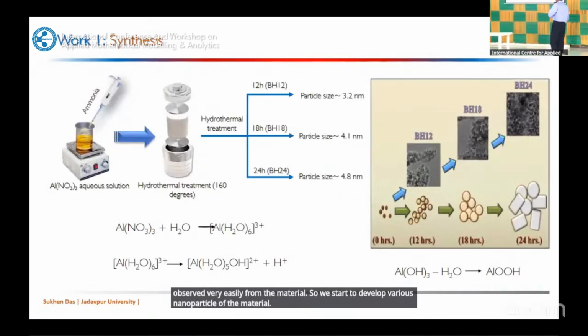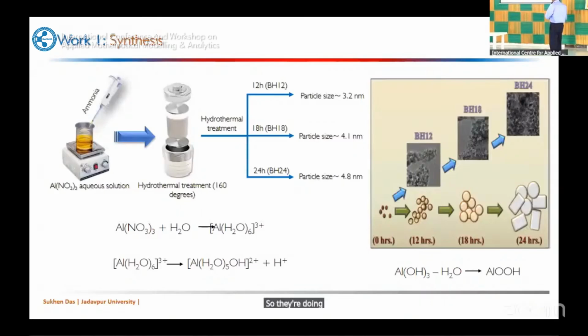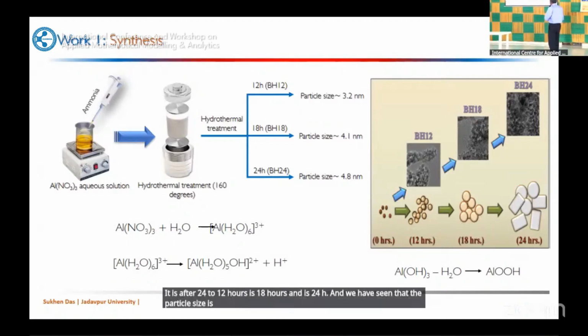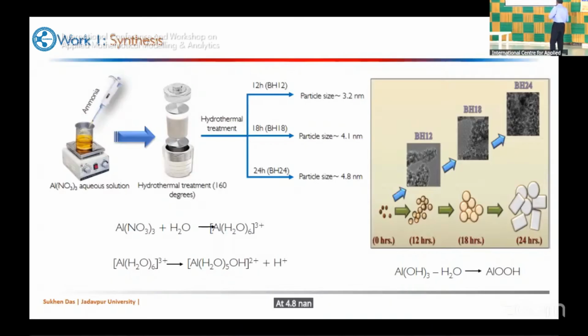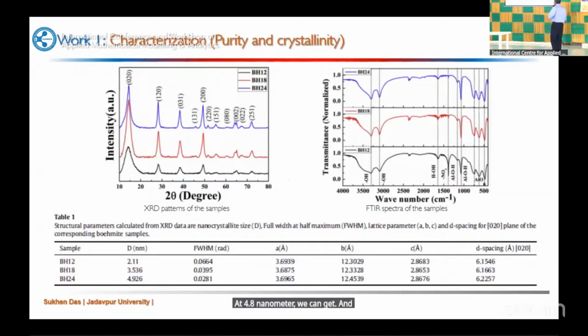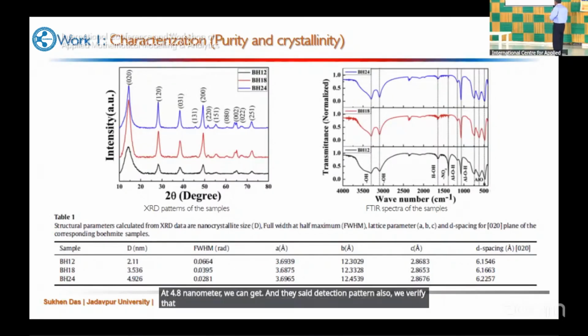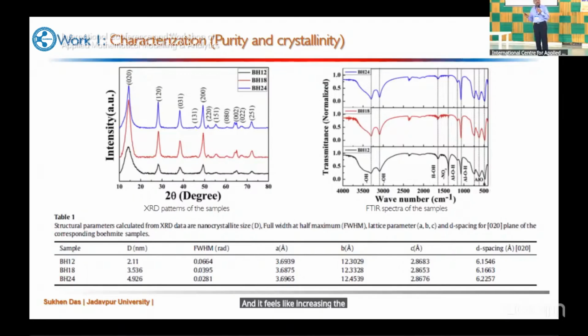Here we can see that from the hydrothermal process we have developed some Boehmite material after 12 hours, 18 hours, and 24 hours. And we have seen that the particle size is very small: 3.2 nanometer, 4.1 nanometer and 4.8 nanometer. And from the X-ray diffraction pattern we also verify this. For 12 hours it is the black one, and for 24 hours it is the blue one, because as the time increases, the crystal size increases. So as the crystal size increases, the surface area of the material decreases.